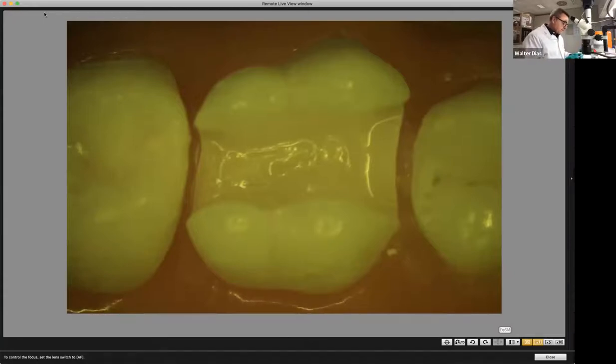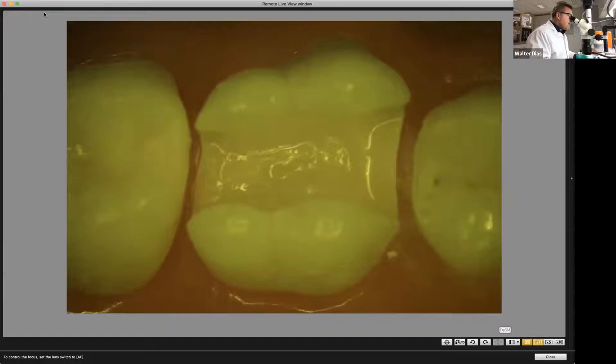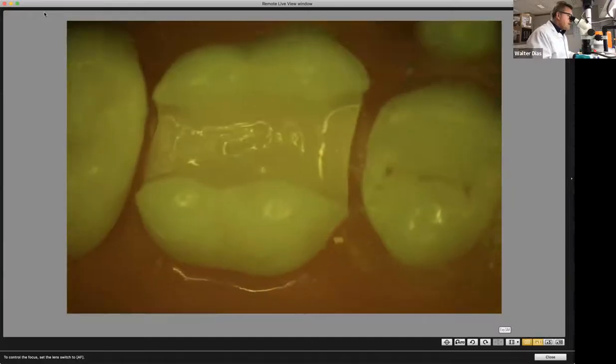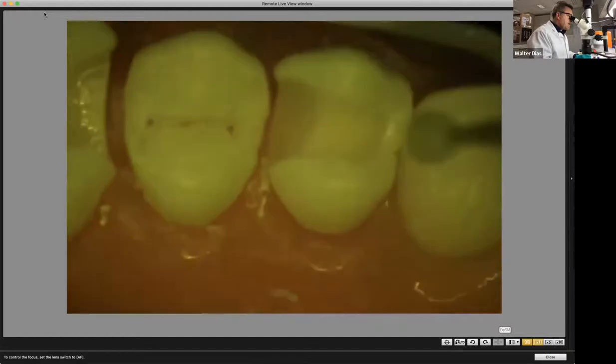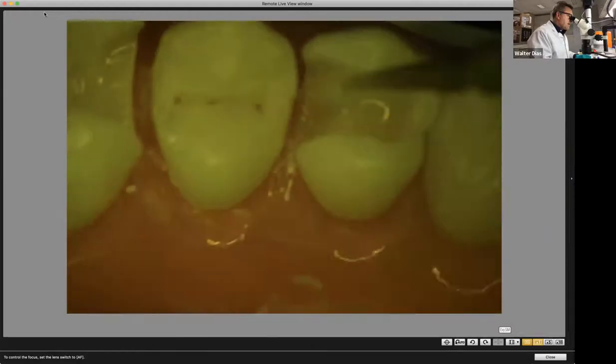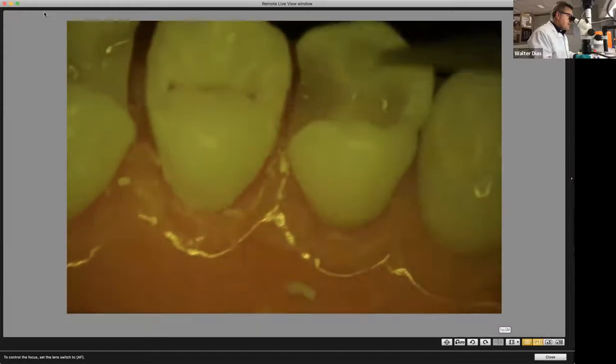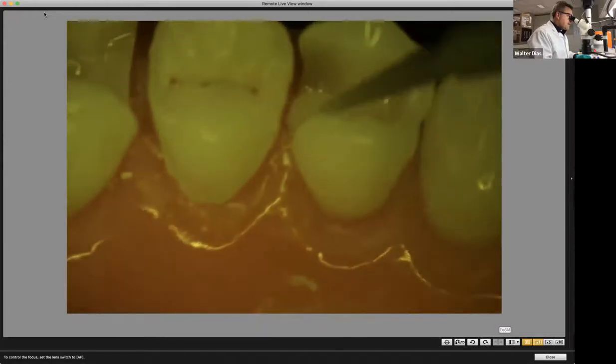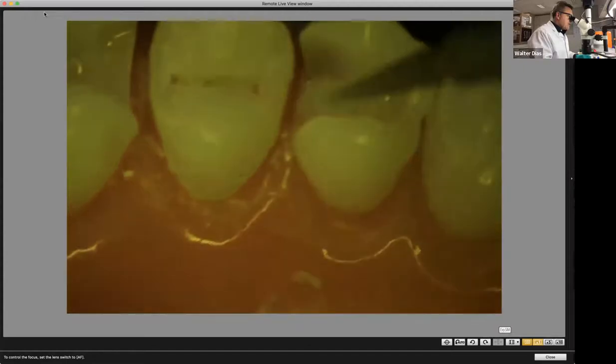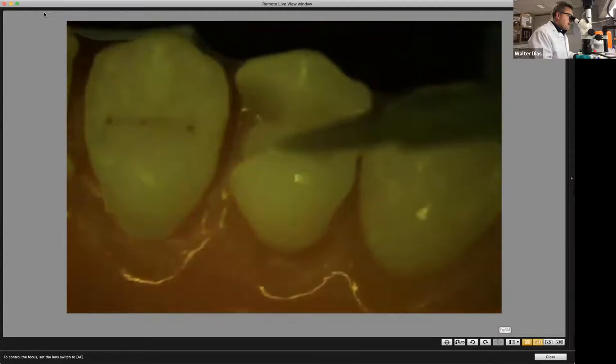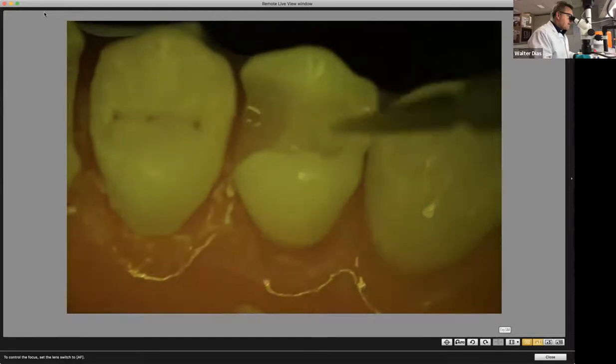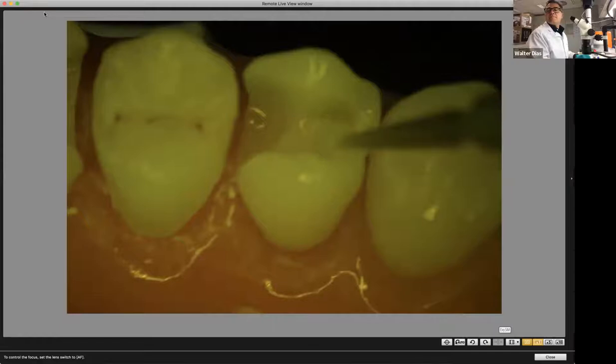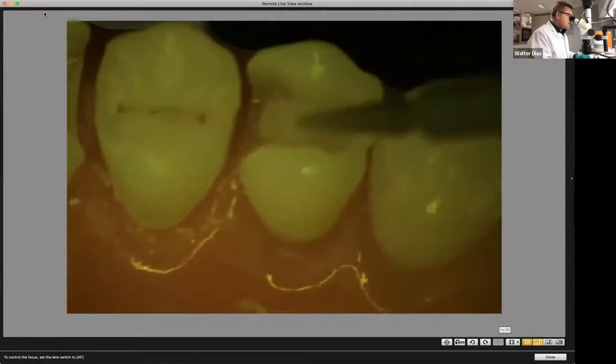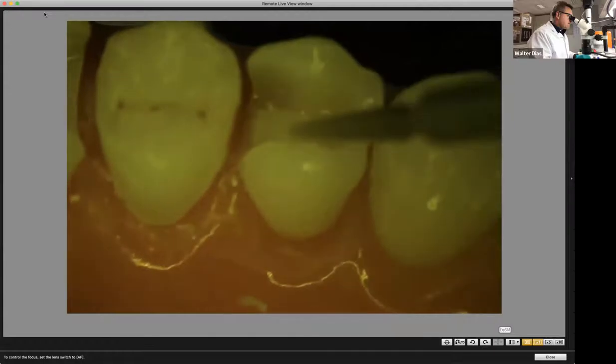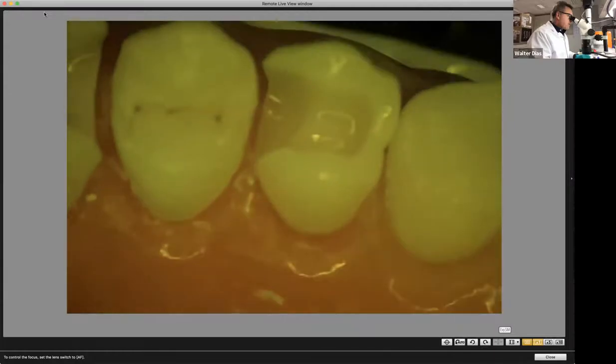What you need to do is apply the adhesive. Let's say you see an area where the adhesive is not properly placed. Here it is. Let's do the premolar here. If you see a deep area, what you're going to do is apply the adhesive in excess, always in excess. Yeah. Then spread it around on the enamel. Then you massage the unetched area, respecting those 20 seconds. All right. And after that, we're going to remove this excess.